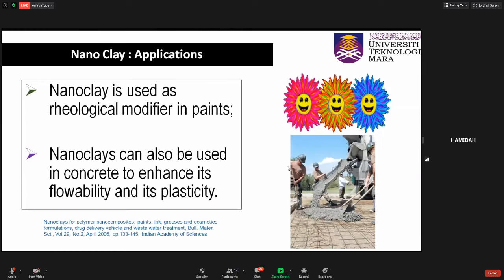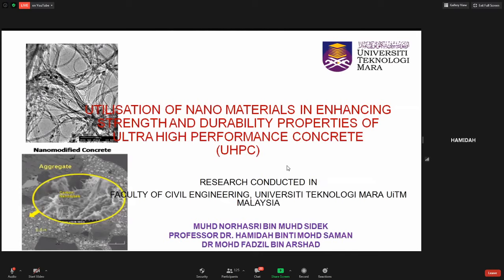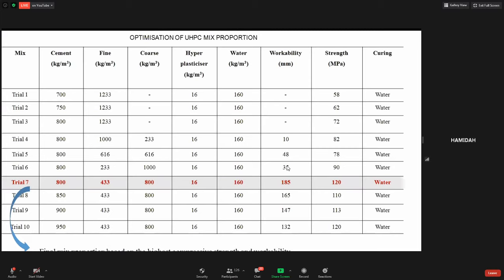Research works have been done in the Faculty of Civil Engineering, Universiti Teknologi Mara, UiTM, on utilization of nanoclay in producing ultra high performance concrete or UHPC, and a series of trial mixes were experimented to determine the optimum formulation with high workability UHPC, incorporating nano metaclay and nano metakaolin. It is an objective of the study to establish ultra high performance concrete made of nanometaclay or nanometakaolin with water curing but can achieve similar strength as those of UHPC made of other materials cured in elevated condition.